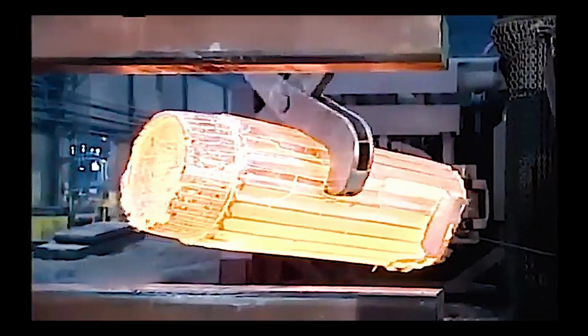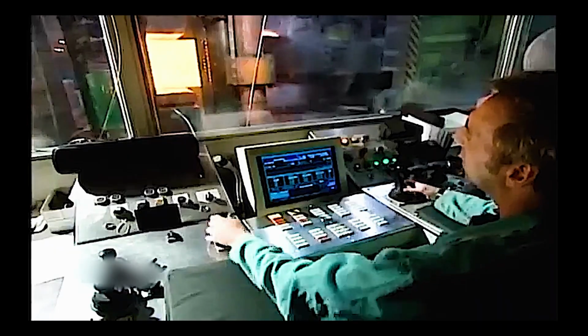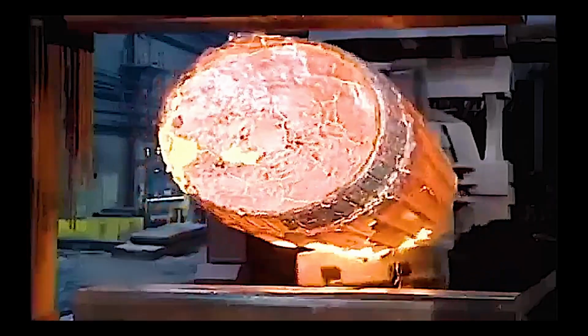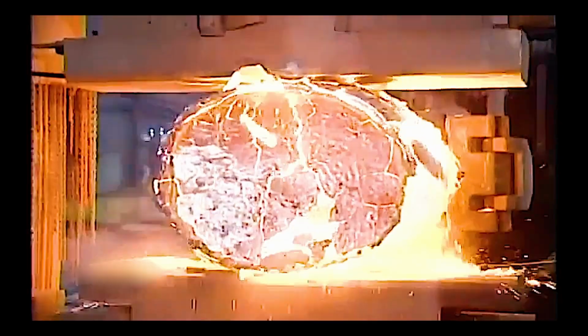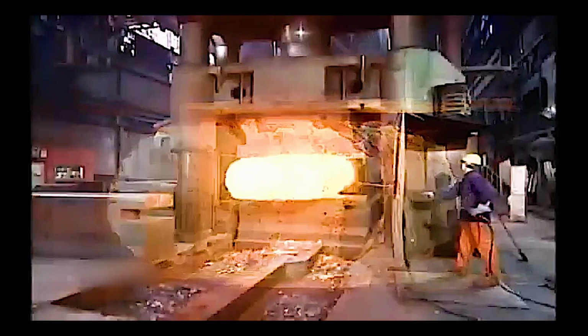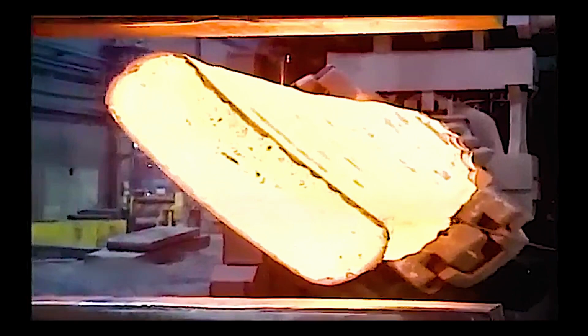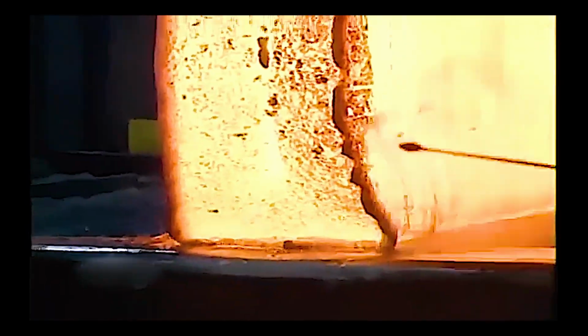To create large forgings, a forging press is used. This machine, equipped with forming dies, applies thousands of tons of pressure, crushing the ingot against the die. As the steel oxidizes from air exposure, a high-pressure water gun removes rust scales. The ingot often passes through the die several times or through a series of dies, gradually forming the final shape.